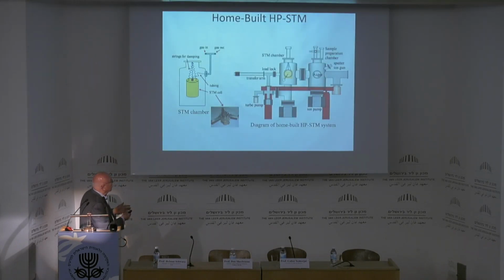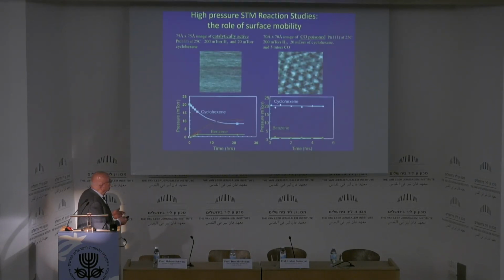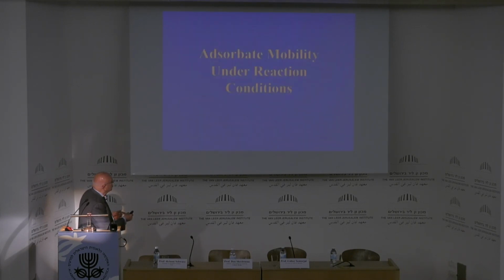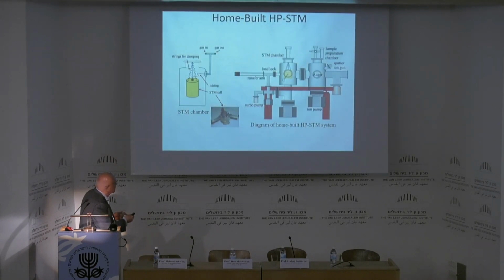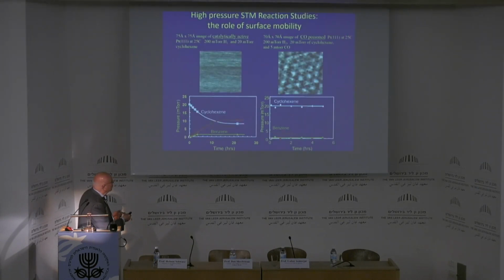Now, the scanning tunneling microscope shows mobility on the surface. If you do a reaction like cyclohexene dehydrogenation to benzene, or hydrogenation to cyclohexane, and you look at the surface, you see absolutely nothing. Why? Because these organic molecules are moving on the surface, at about 100 angstrom per millisecond, and so as it moves, it gives you no picture.